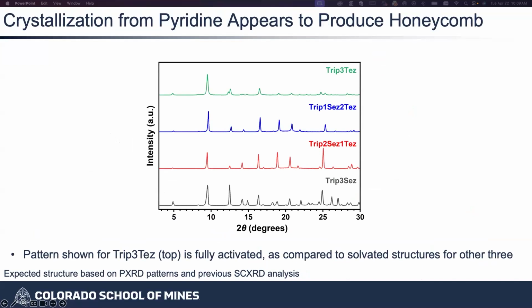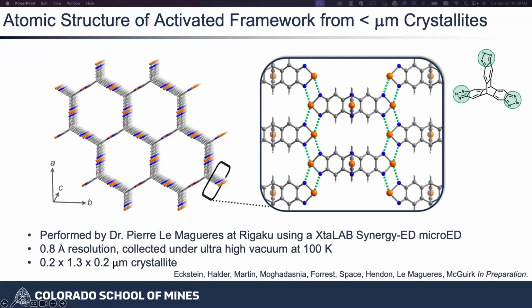And then we could see that these did align with the honeycomb type lattice for all of our different systems. And then really incredibly, and this was done by Pierre down in Houston, we were able to see through microED that we did have that honeycomb type system. And I can't really emphasize enough how small these tiny little crystallites are. This really blows my mind that we were able to get this structure.